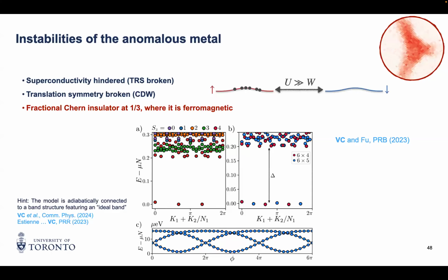Yeah, and the competing state at that filling is a charge density wave. The two have different sigma xy, which really pushes you into measuring that Hall conductivity. The way to measure that conductivity is to look at that particular filling, apply a magnetic field, and measure the dependence of any quantity as a function of magnetic field at that filling.